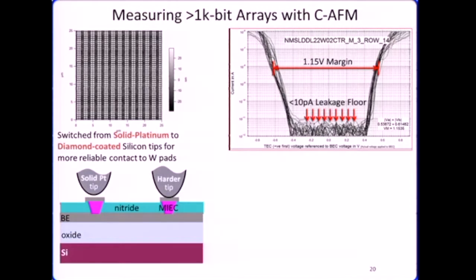They came down with either a solid metal tip or a much harder diamond coated tip that made a robust contact. And they went in and did IV measurement at every single contact with full automation. And once they have selected the right film for the process, they got excellent yield. And in some cases, every single device performed as their expectation. And they found that the expected IV performance was good for 100% of the devices. So these are 1200 IV measurements laid on top of each other. The other interesting thing is, they found that the leakage current in their device was less than their expected value. So with this level of data, they were confident that they could scale this process and actually go to production.